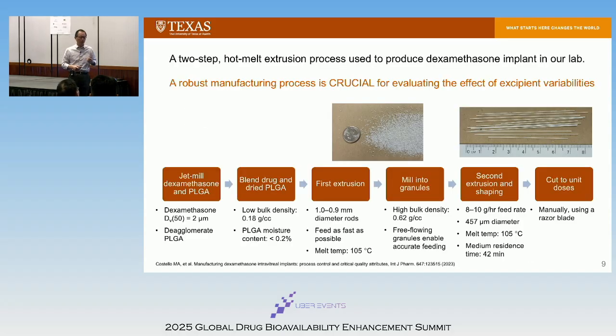And then the key thing in making the implants is dimension control. That dimension has to be extremely tight, right? To do that, your material has to absolutely flow. So we did a two-step extrusion process. I have a video here. First step, we just basically mix them together. We don't really use a die. Material goes through, we make large rods, and we break them down to fine particles.